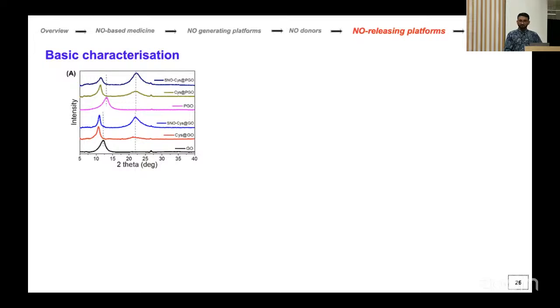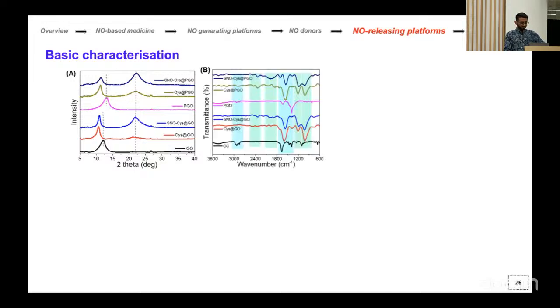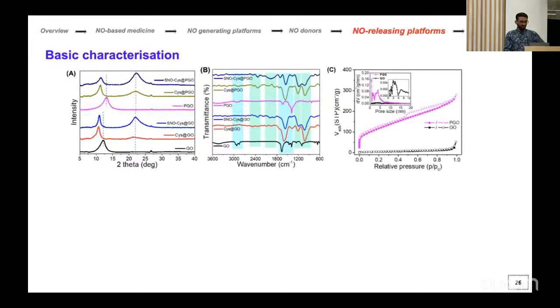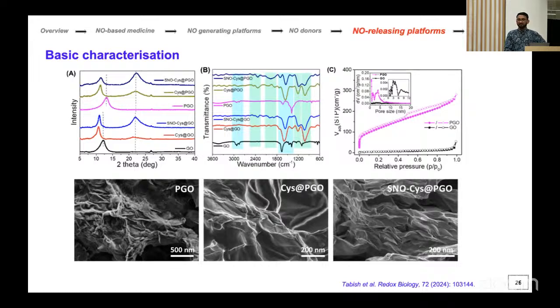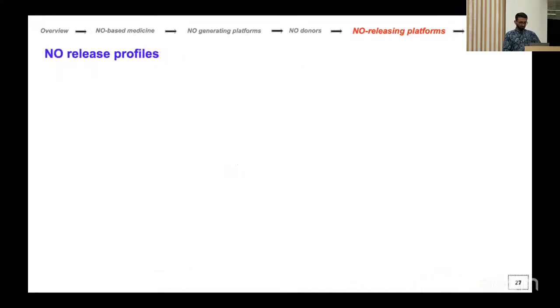Okay, so that's the basic characterization to show the XRD with cysteamine and then with nitrite. There is a shift in XRD peaks, and then also FTIR to show the introduction of new functional groups, and then BET specific surface area to show that porous graphene oxide has higher specific surface area in comparison to its counterpart graphene oxide. And then scanning electron microscopy and transmission electron microscopy images to show the sheet-like structure, and also to show that the functionalization is not affecting the sheet-like morphology of graphene.